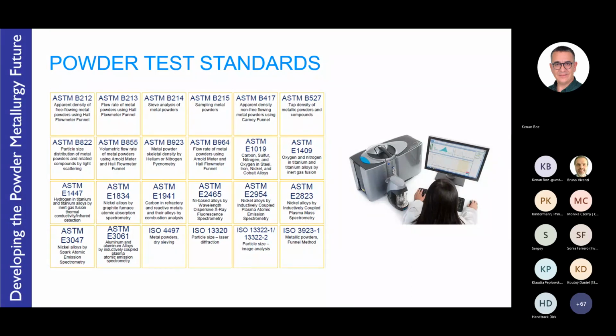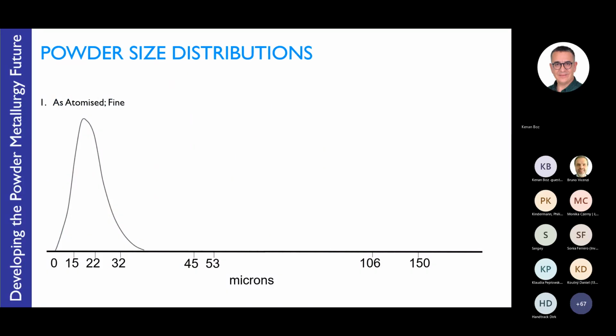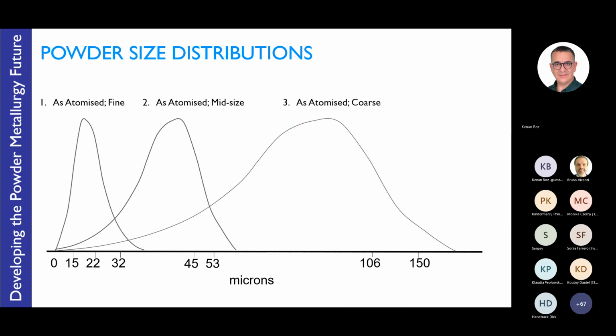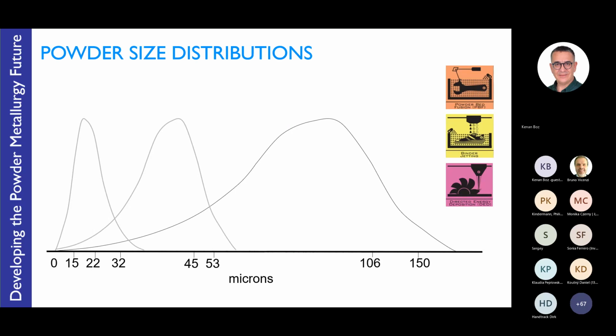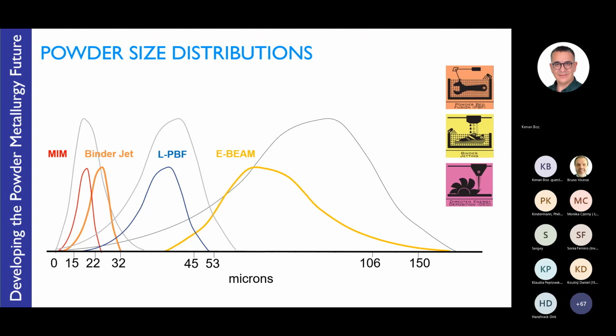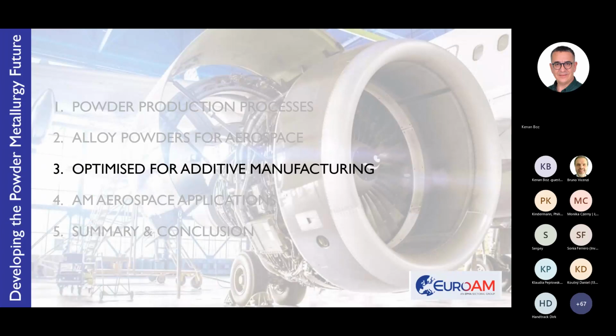So now talking about one particular aspect, powder size distributions, of course, atomizing fine powders as well as mid-size fractions and coarse powders. And these can be atomized, targeting the different distributions for the different additive manufacturing processes. Fine powder is typically used in metal injection molding, but also now finding interest in binder jet printing. Of course, the laser powder bed fusion, electron beam, and direct energy deposition processes, and even coarser or full fractions used in hot isostatic pressing of net shaped components, but also a very useful technique for consolidating the microstructure and eradicating pores. So optimized for additive manufacturing.